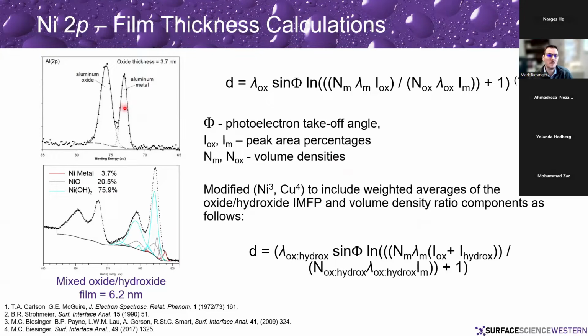So say for the aluminum metal, you have so much under the curve, aluminum oxide under the curve, plug that in along with calculated inelastic mean free paths, and you can pull out and say, okay, I've got an oxide thickness of 3.7 nanometers. Great. Works well if you have just a single species or single type of overlayer.